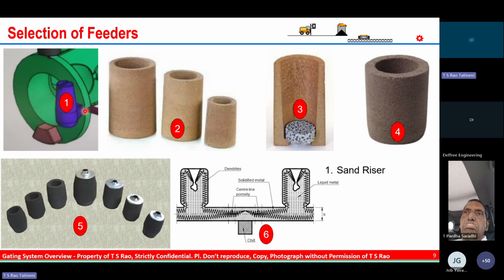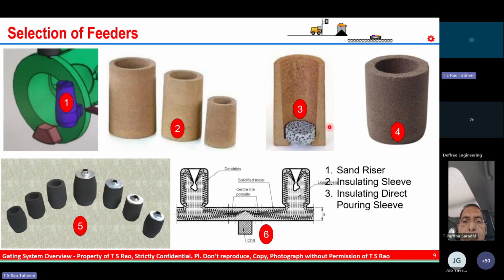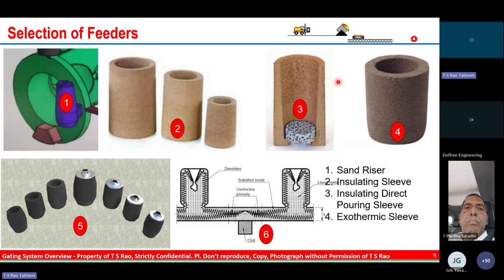The first one is a sand riser where the MEF, the modulus extension factor, is 1. The second one is insulating sleeves where the modulus extension factor would be about 1.5. The third one is insulating direct pouring sleeve. Here also the modulus extension factor is about 1.5. The fourth one is exothermic sleeve. Here the modulus extension factor is about 1.67 to 1.71.